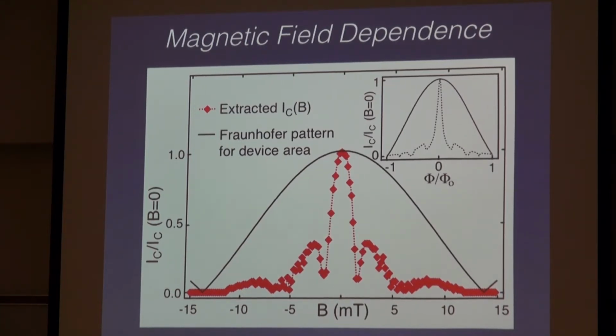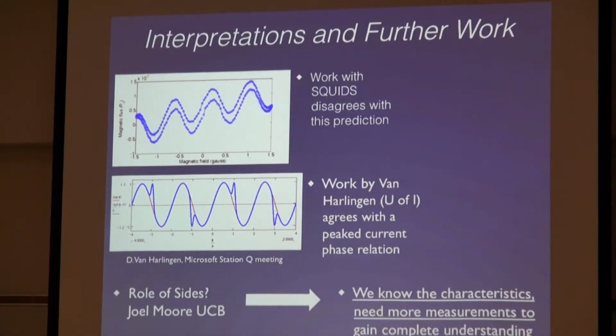Now for this first zero, I should have mentioned at the outset, a lot of things can make your Fraunhofer pattern go bad. We spend a lot of time working through those various ways. You can get elevation of these zeros away from zero critical current, but usually what happens is that all of the dips are elevated off. This switching between up and down, and hopefully as we do more work, we might see another up here and another down here. When you have a single flux through the device, this is when Majorana physics should dominate. So one of the working theories is that this peak here is really related to the current that's being contributed by the junction from the Majorana fermion. But I don't know. We haven't worked out the details of that yet. That's ongoing work.